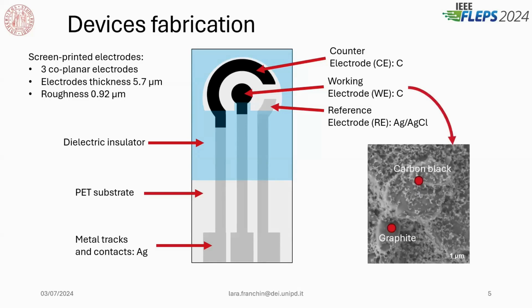In fact, here we can see a picture of the ink that we used. In this case, it is the working electrode. The small flakes are the carbon black, which is one of the components of the ink, and the bigger flakes are the graphite, the other component of the ink that we used. We also studied the thickness of the device, which is around 5.7 micrometers, with a roughness of around 0.92 micrometers.